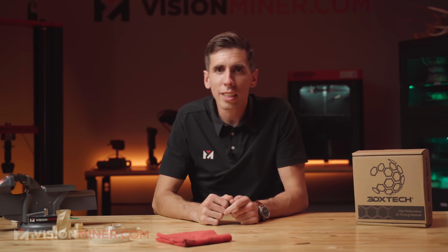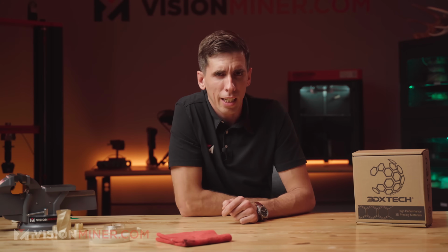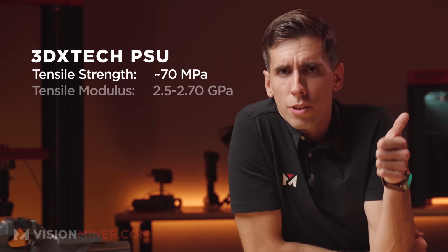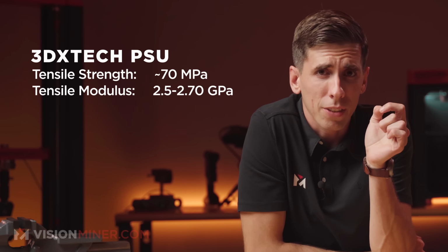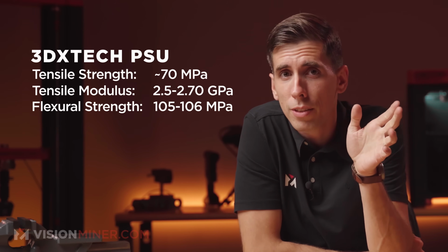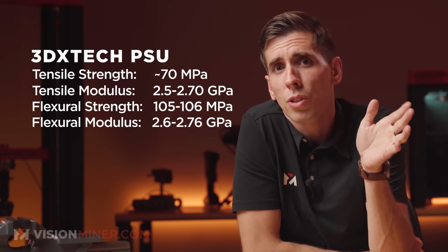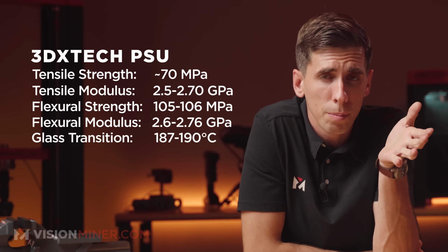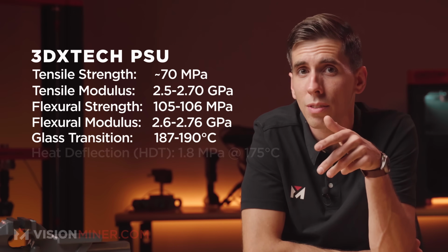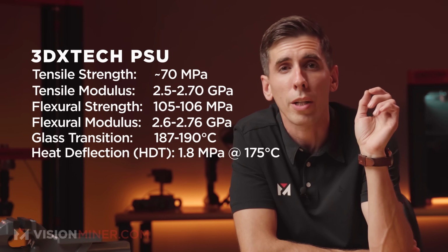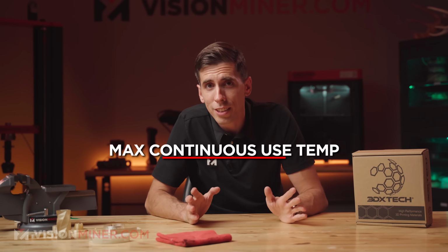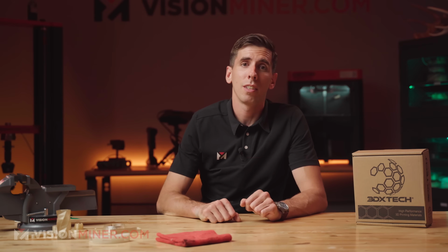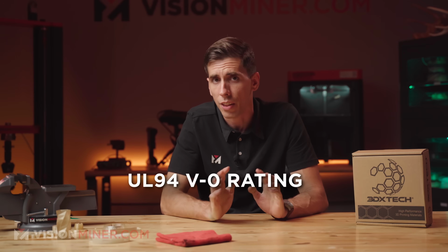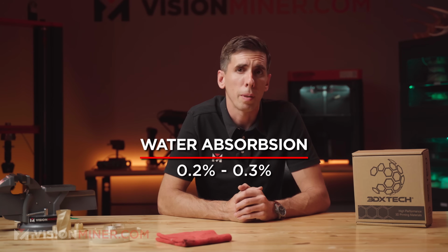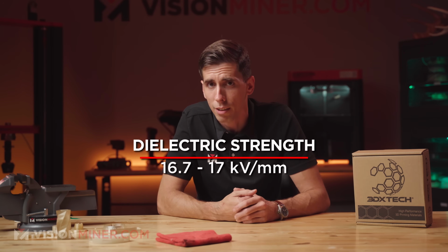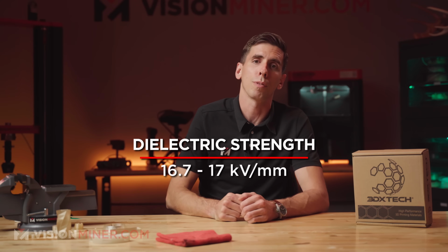All right, so let's get into some technical details straight from the TDS. The tensile strength is about 70 megapascals. The tensile modulus, 2.5 to 2.7 gigapascals. The flexural strength is 105 to 106 megapascals. Flexural modulus of 2.6 to 2.76 gigapascals, with a glass transition temperature of 187 to 190 Celsius and an HDT at 1.8 megapascals of about 175 Celsius, giving it a max continuous use temperature of about 160 Celsius. It's also got that UL94 V0 rating, depending on the thickness, and water absorption of about 0.2 to 0.3%, with a dielectric strength of 16.7 to 17 kilovolts per millimeter.